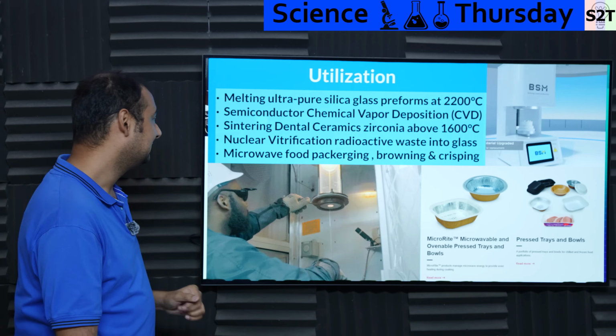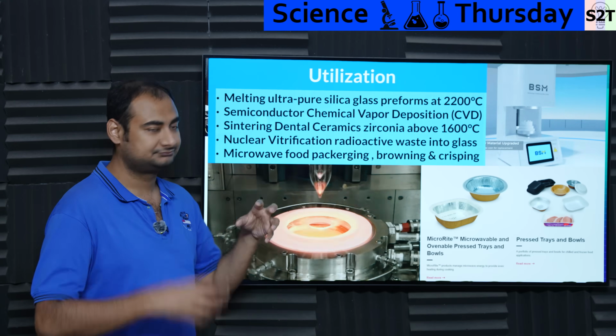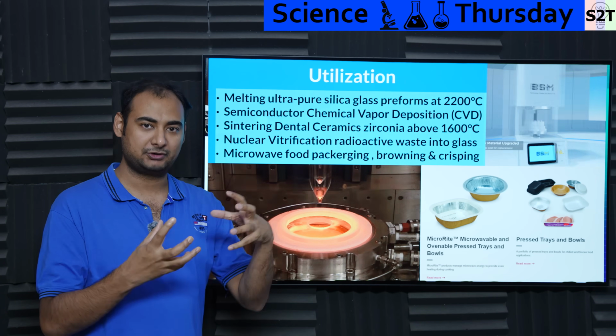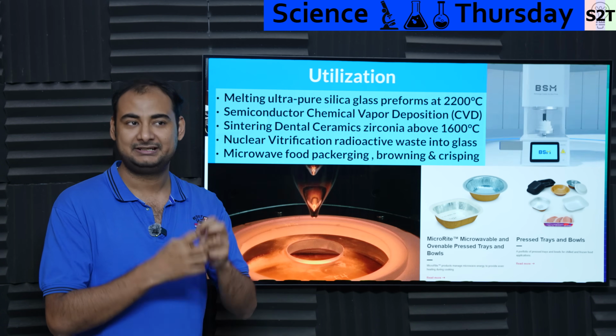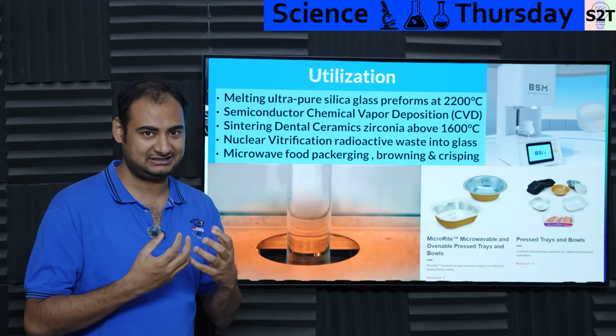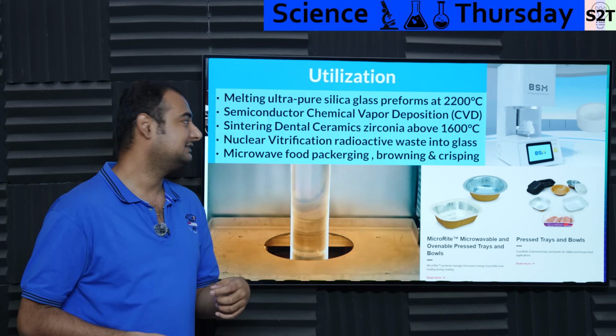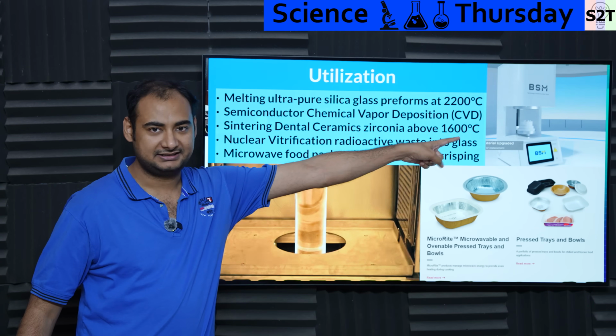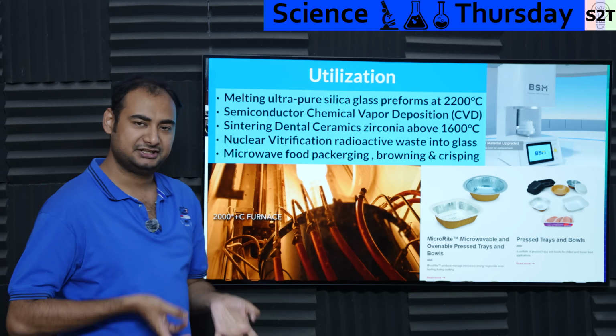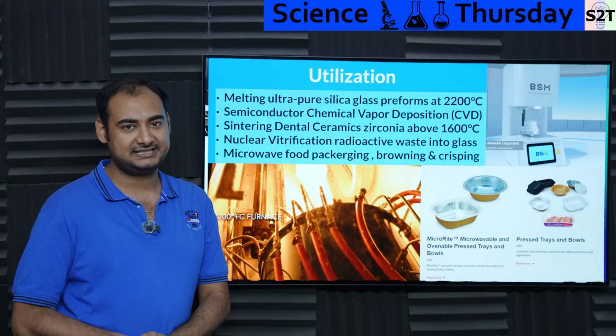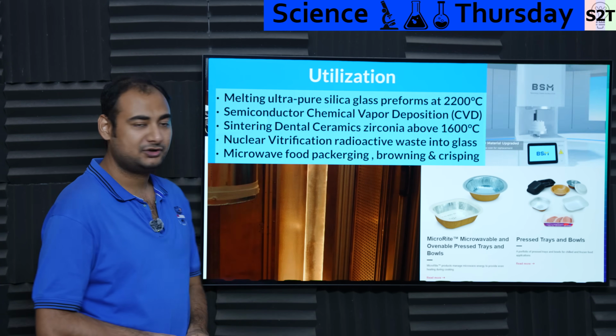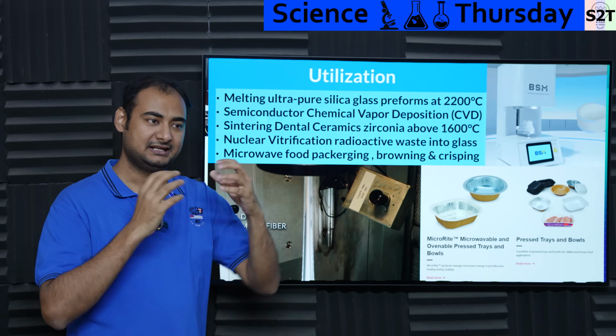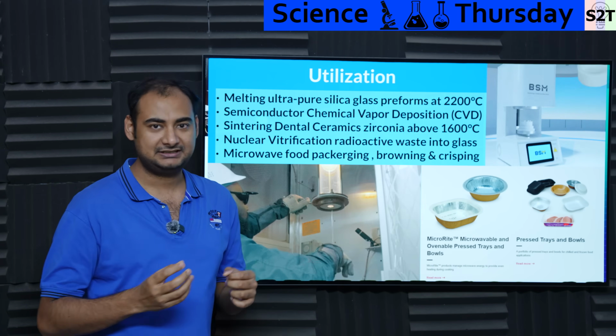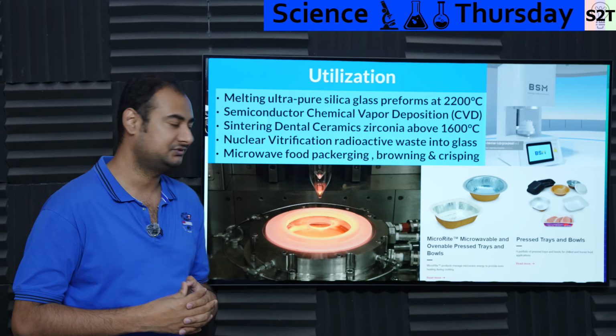have that 99.99999% purity. Then you have sintering. Basically, what if you have a lot of powder attached via binder? It's not good enough for human teeth application. So for my teeth like this, they will put it in a cooker like this. This cooker will pull a vacuum and then heat it up to 1600 degrees Celsius. At that point, those powder grain boundaries will start to merge with each other, and then you get a crystal. That puppy is strong enough to survive your teeth, dental use.